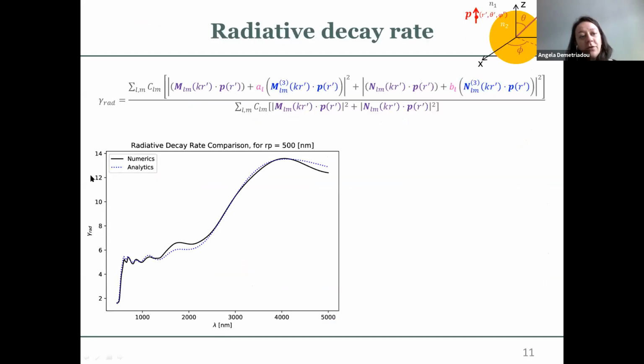So going back to the radiative decay rate formula that we had before, you can plot the full result, which is the blue dashed line here, and the black one is numerical results. And you see this is for a very, very large spherical nanoparticle. It's a radius of 500 nanometers. And you start seeing the separate modes from each multipole.